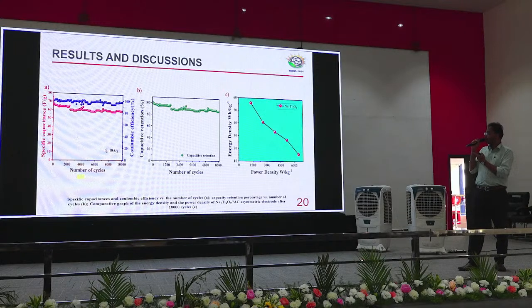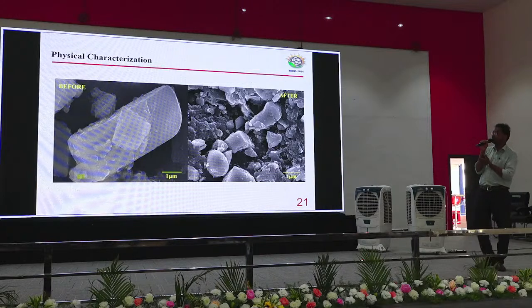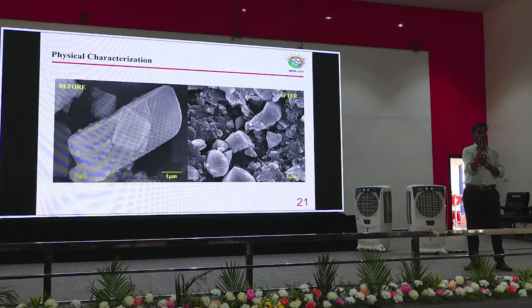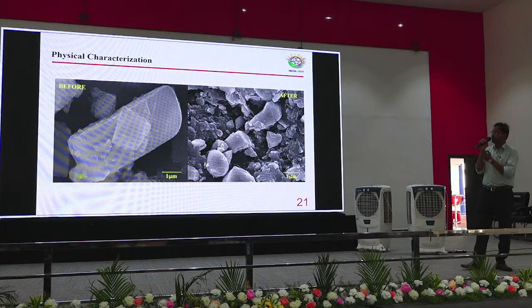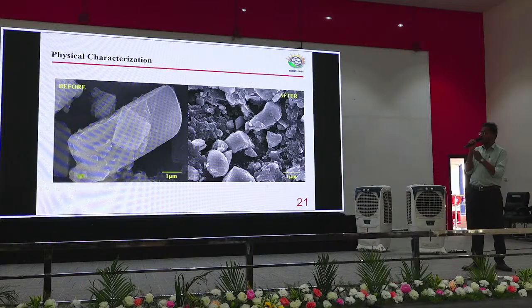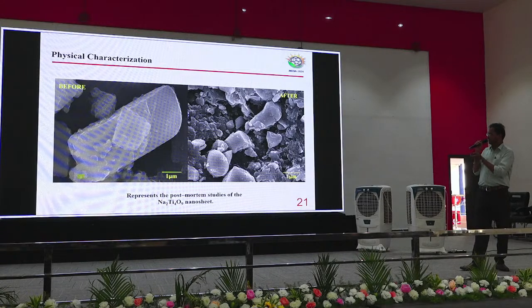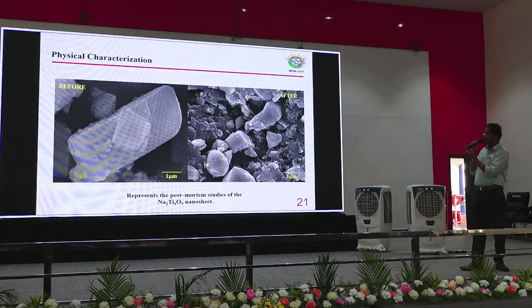So around 6500 power density and 55 watt hour per kilogram energy density we have calculated. Then after finishing all my studies, in the final stage we calculated the cycle and capacity retention studies. Then move on to postmortem studies to check that the material is in good condition. So we get the before morphology, nanosheets. After my studies are complete, we also did the same morphology studies, as in this figure. So before, nanosheets in the A figure, and after, the morphology studies are concluded here.